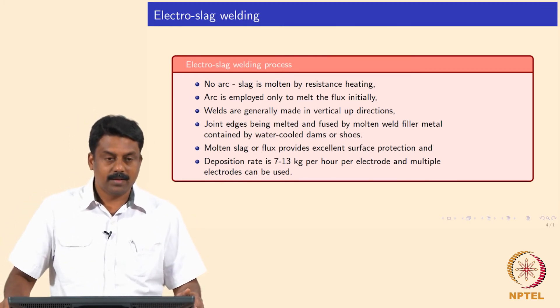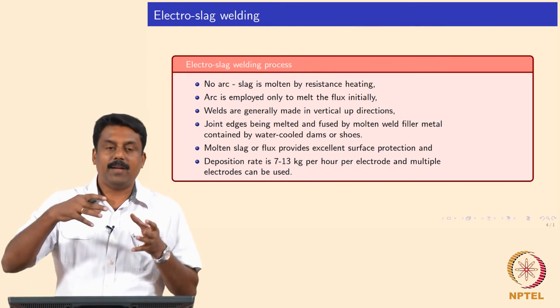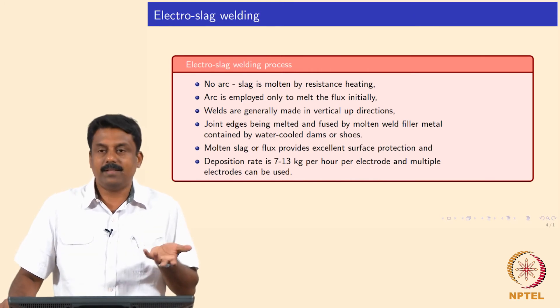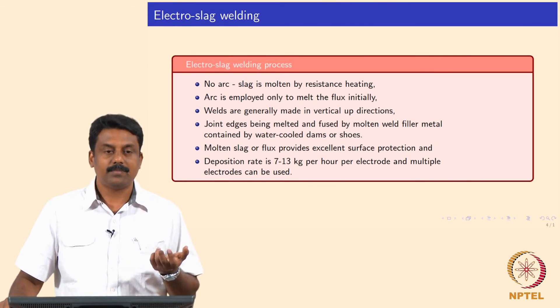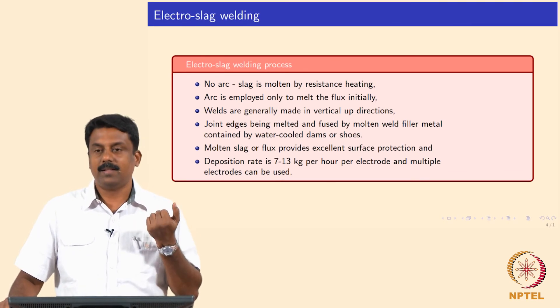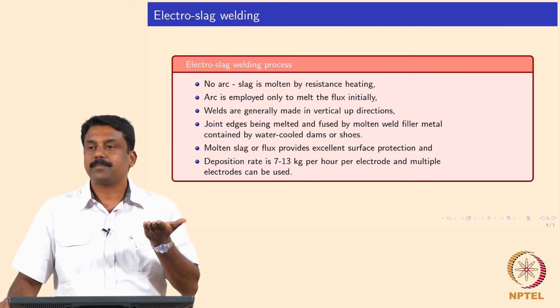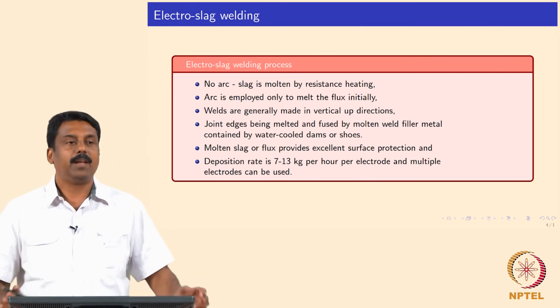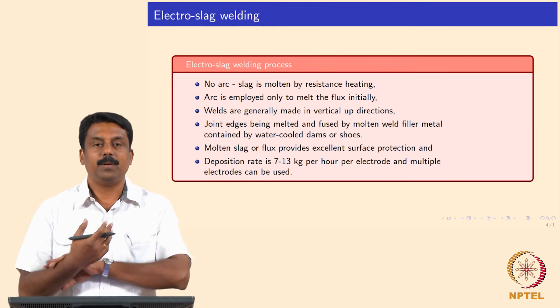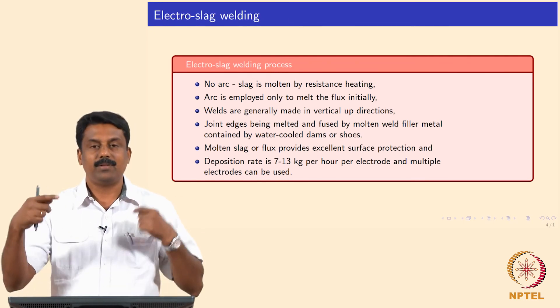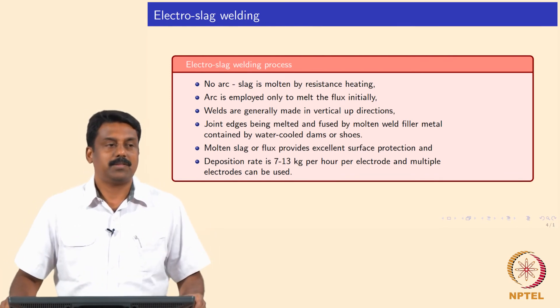Student question: Is the slag initially decomposed by the arc? Yes — initially when you are adding just flux powder, achieving resistance heating is much less efficient since flux is a powder. So you first strike an arc so the flux can be melted by the arc heat. The moment the flux melts and decomposes, you form slag, and the slag flows up to reach the electrode tip; once the electrode tip is immersed in slag, the arc extinguishes. You can achieve huge deposition rates — up to 30 kilograms per hour — and with multiple electrodes the process is like creating a cast structure.